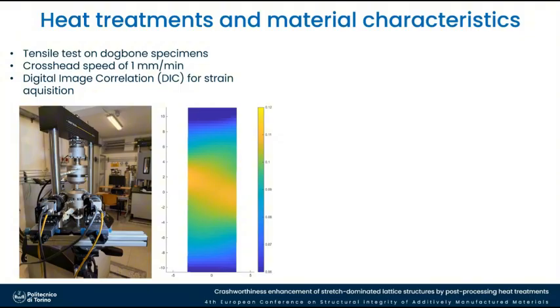Then we move to the characterization of the mechanical properties, starting from the tensile test. And we performed this with digital image correlation to acquire the strain field, so that we were able to see the whole tested area, the whole strain gauge area, but also to identify the strains in correspondence of the necking zone.